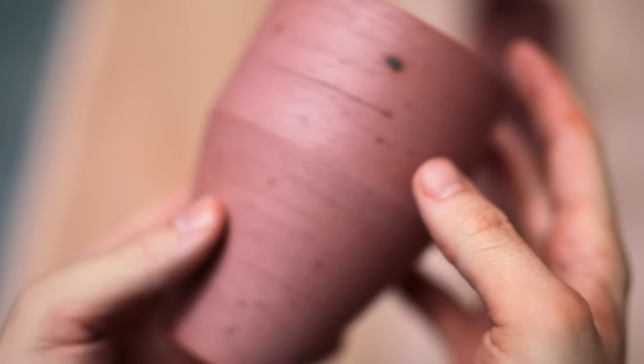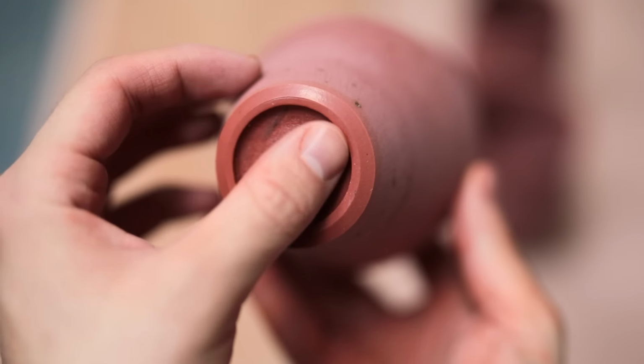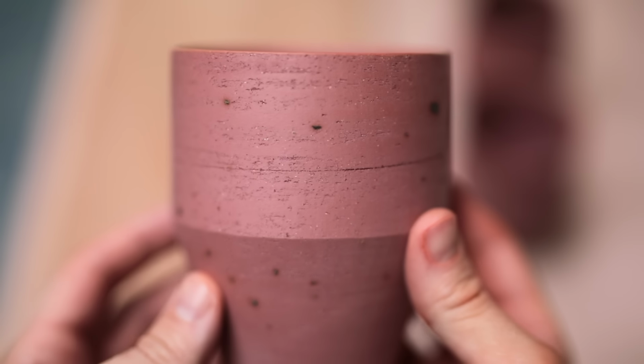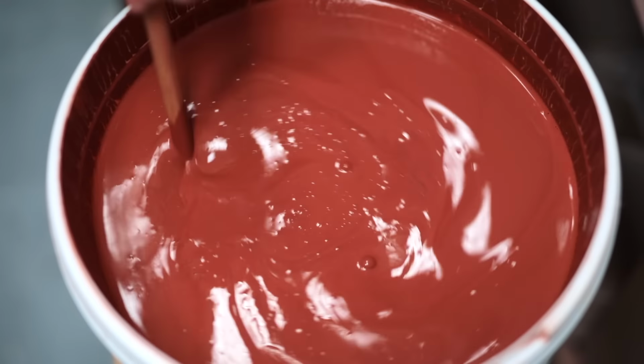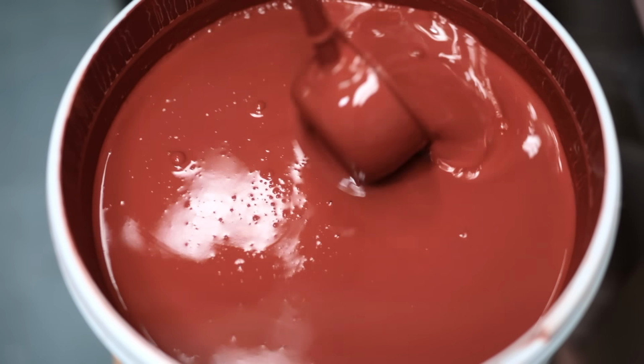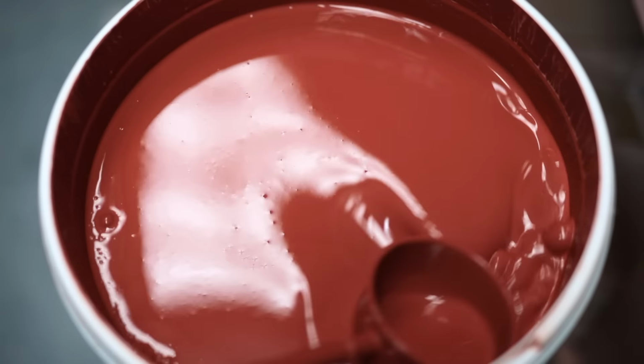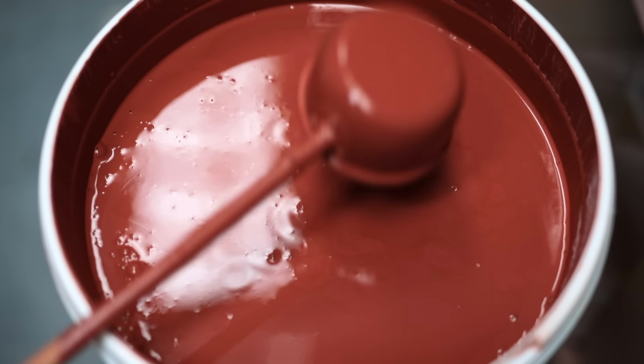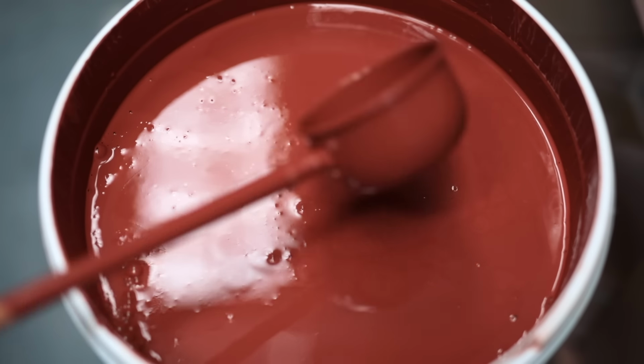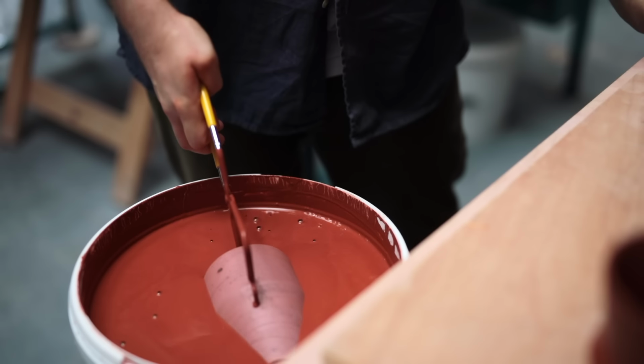At this stage, with the pot's bases waxed and the glaze mixed, I can move on to dipping them into said glaze with a pair of tongs. After a few days, all the heavier material in here has settled to the bottom, so before it can be used, it's given a good mix. Each vessel is then held with a pair of tongs, submerged into the glaze for about 4 or 5 seconds. It's then taken out, the excess allowed to drip away, and then I rotate it around in place to try and get the droplets to settle evenly across the pot's shape.